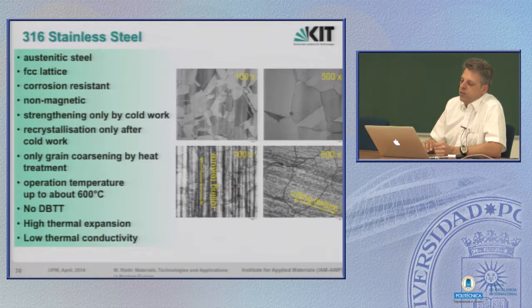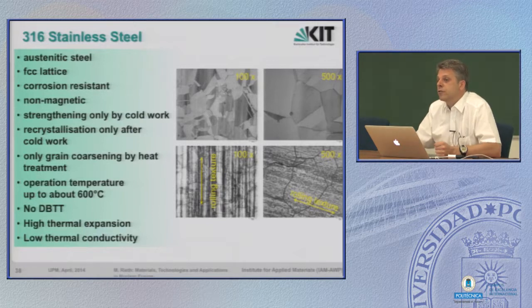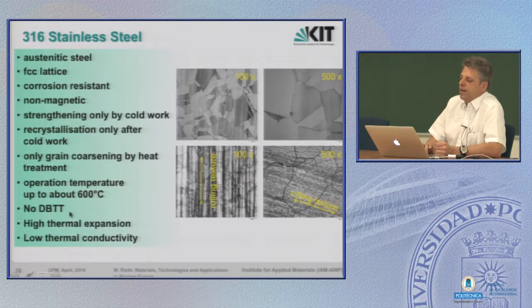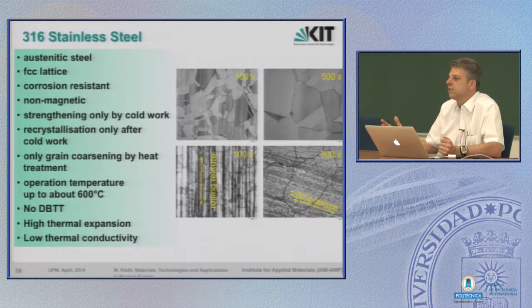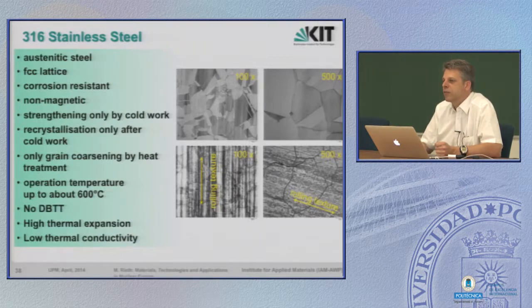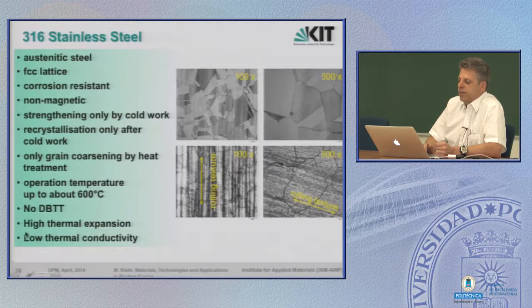The operation temperature, nevertheless, is up to about 600 C. Definition of operating temperature in energy application corresponds to creep strength for 100 MPa and a lifetime of 100,000 hours. This is more or less the definition of operation temperature. Since it is FCC structured, you know it by now, it shows no DBTT. So it is perfectly well suited for low temperature applications, but again, in fusion reactors, the low temperature applications are mainly due to magnets and cryostat, so here it fits quite well.